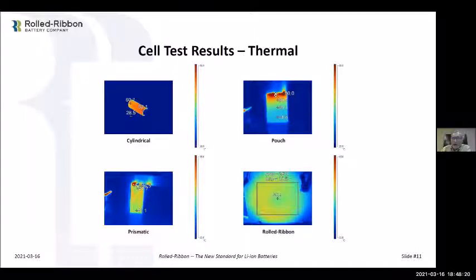If you look what a pouch cell does, again, same thing. You see really high here at the terminals, very cool at the bottom because all the current started here, very little current flow. Current flow increases across the sheet as you get to the top here, and then the terminals, and it's all concentrated. Uneven gradients, the cell wears unevenly, and the results are predictable. Here's a prismatic, again, the same thing. And if you look at the temperature inside, it's much higher than the surface temperature. And you have the same issue here with the prismatic. The prismatic actually masks some of this effect here because of the metal can. So it does a diffusion, but the temperature inside that can, again, is 20 degrees C hotter. Okay, and then you take the Rolled-Ribbon here, and you can see it runs very, very cool the entire time. Uniform distribution of heat. So you're looking at this thing again in the thermography. Runs very, very cool compared to the others.